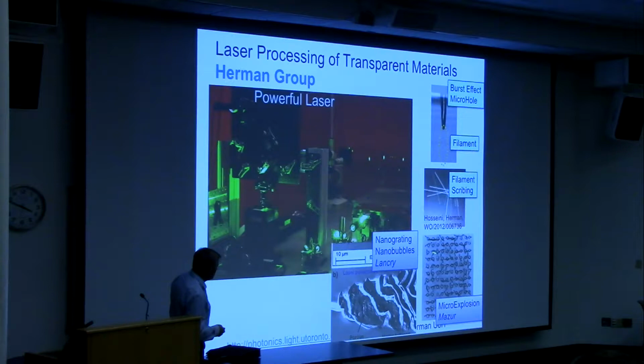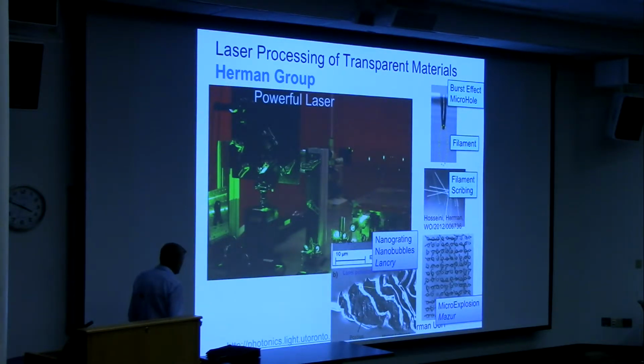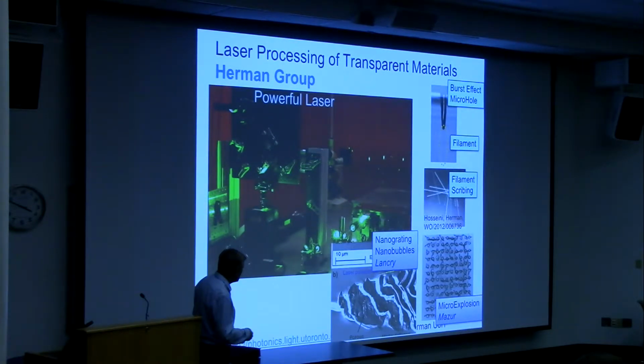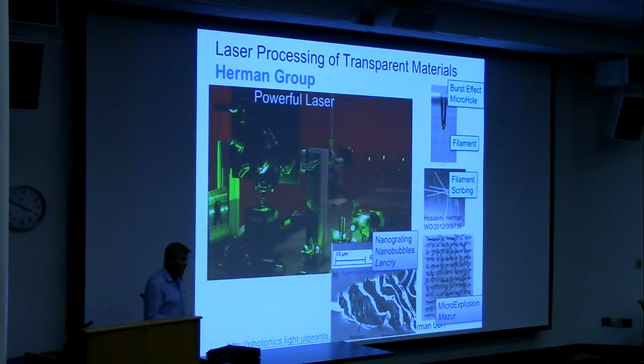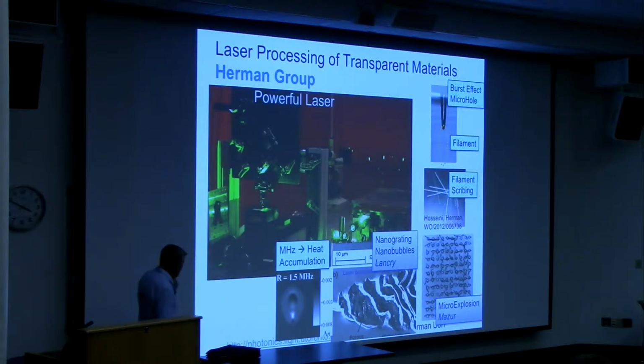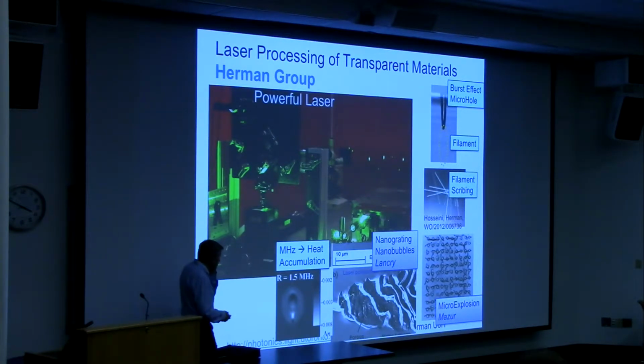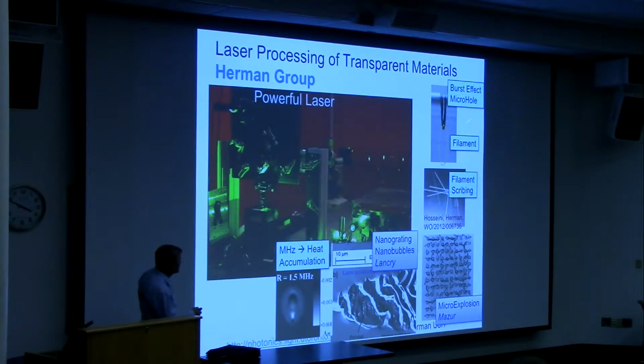But if you look closely at modification, for example, in fused silica, you end up forming nanobubbles, as well as, with polarization control, you can align these self-assembled gratings over many pulses. So this internal morphology consists of, say, positive index changes that look white in this micron scale view, and on the nanoscale underlying that are birefringence effects, because these are directional modifications, and porosity, which leads to stresses and index changes. It looks kind of ugly, but the outcome is you are making 3D devices with some benefits. So if you want to avoid this morphology, one way to smooth things out is to go back to these high repetition rate effects, this heat accumulation effect, and you can get these very smooth waveguides.